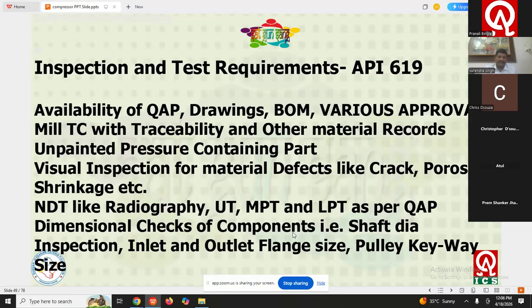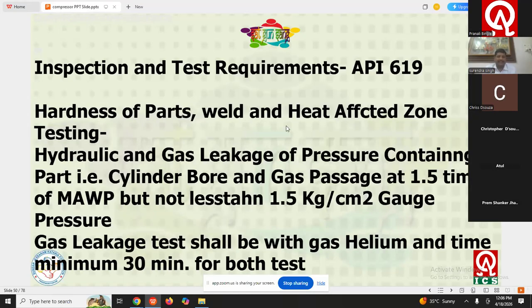Again, dimensional check of components for the shaft diameter, inlet and outlet sizes, pulley, key-way, etc. You have to check. Same, hardness of parts, welds, you have to check at parent metals, welds, and the heat affected zones, hydraulic and the gas leakage of pressure containing part. You have to check. The same requirement is given that the hydraulic pressure shall be 1.5 times the maximum allowable working pressure. So in this standard, that is in API 619, if my allowable working pressure is 60 kg, my testing pressure will be 1.5 times, means the testing pressure will be 90 kg per centimeter square. And again, a condition is given that not less than 1.5.